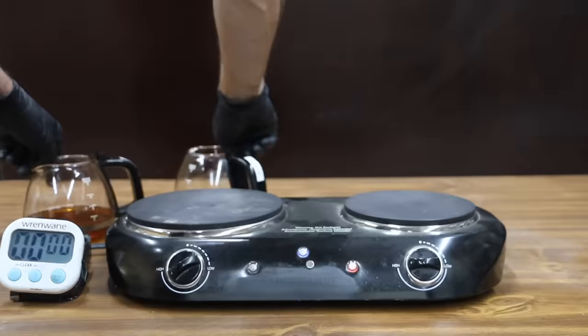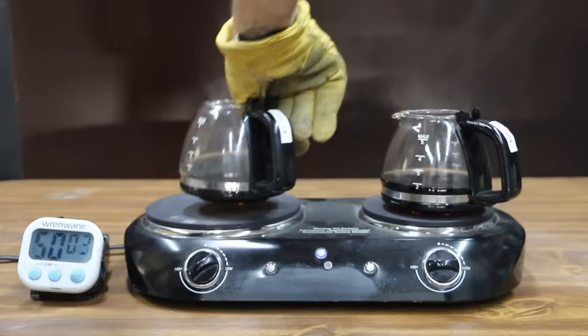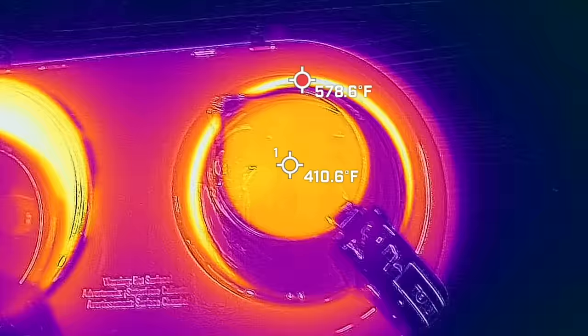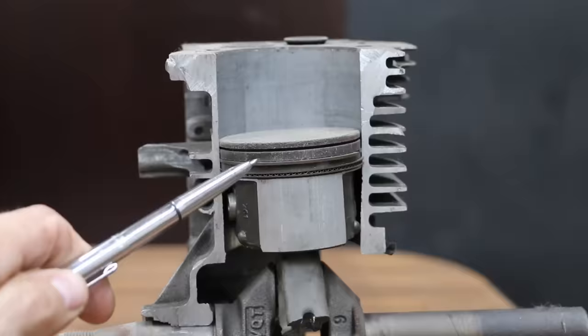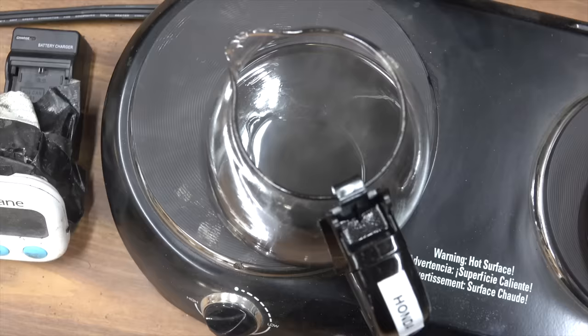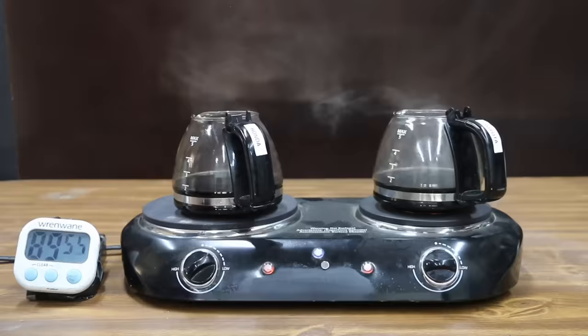I'll first compare the Honda against the Toyota. Each of the pots or test containers weighs a different amount, so I'll measure out precisely 200 grams of oil. Then I'll crank up the heat to around 410 degrees Fahrenheit for two hours, rotating the oil containers every 10 minutes just in case one burner is hotter than the other. The official test for this is the NOACK Volatility Test — an ASTM test which exposes oil to a lot more heat than this to simulate engine operating conditions around the upper piston ring area. High quality oils resist evaporation and thermal breakdown. At the end of this test, we'll find out how much evaporation has occurred with each brand.